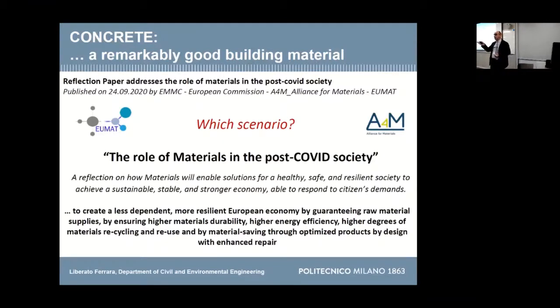For example, Niranjan worked on recycling UHPC. We said the project is a zero waste project simply because we picked up the specimens, we crushed them, and we reused them. We did not dispose of anything on site. In the composition of this material, you have a lot of binder and a low water cement ratio. In your mortar around the aggregate, there is a lot of material which is still potentially reactive. This is a way to address the problem.